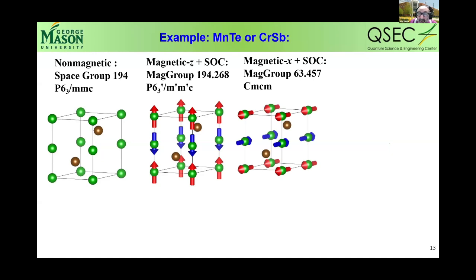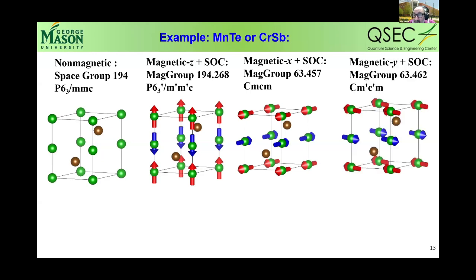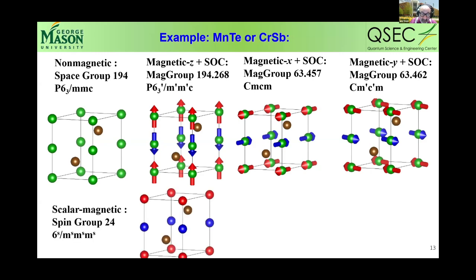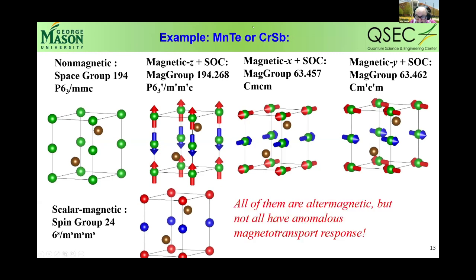If we position our moments along the X direction, that means along the manganese-manganese bond, the metal-metal bond, it's now an orthorhombic, base-centered orthorhombic material. And if I position them along Y, perpendicular to the bond, even though it looks very similar, it's actually a different magnetic group. Now, in Libor's classification, it belongs to spin group number 24, and all three are the same. Now, all these three are altermagnetic, but not all of them have an anomalous magnetotransport response. In fact, only the last one on the right does.